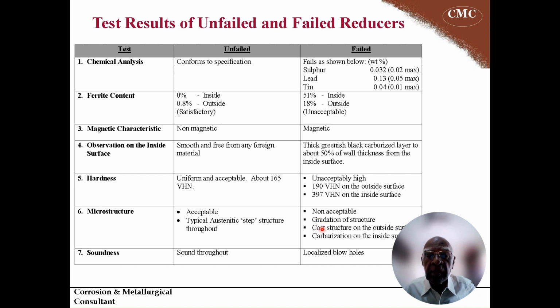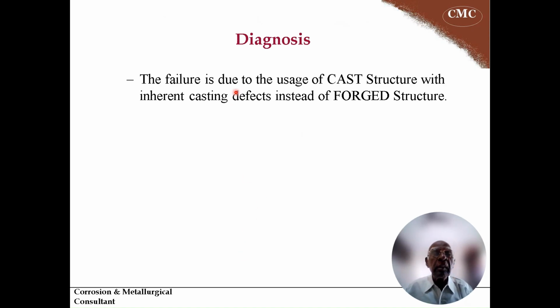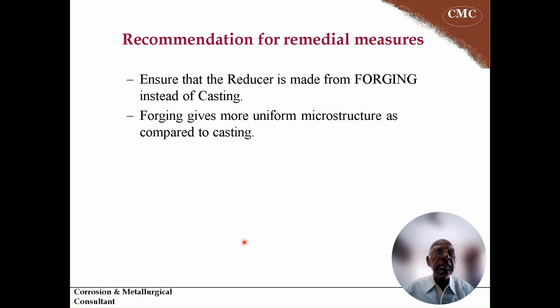There is a non-acceptable gradation of structure, cast structure on the outside surface, and carburization on the inside surface. Due to casting, there is a preferential carburization on these defective reducers. As for soundness, the unfailed one is sound throughout, whereas in the failed ones localized blowholes are present, hence they are defective. So this is the comparison. So the diagnosis: the failure is due to the usage of cast structure with inherent casting defects instead of forged structure. Apparently there is a mixing of cast and forged routes in the supplies made. So a recommendation for remedial measures: ensure that the reducer is made from forging instead of casting.